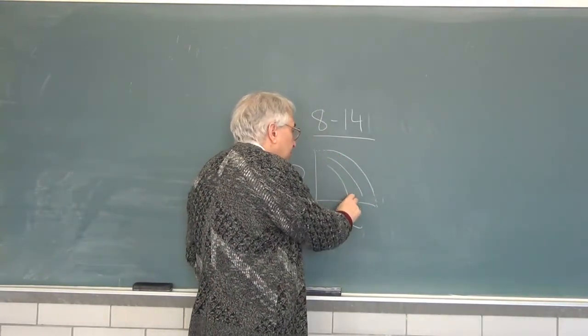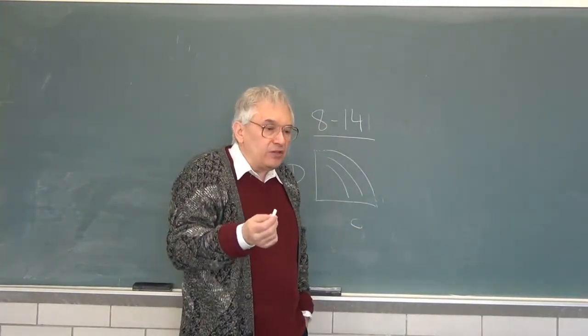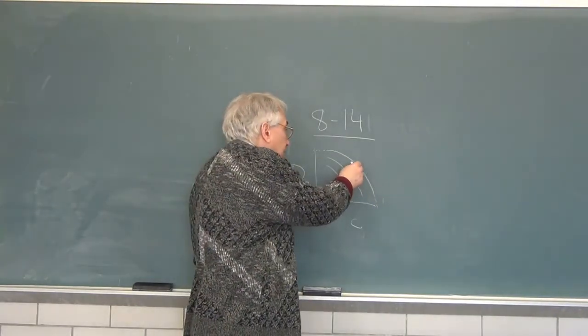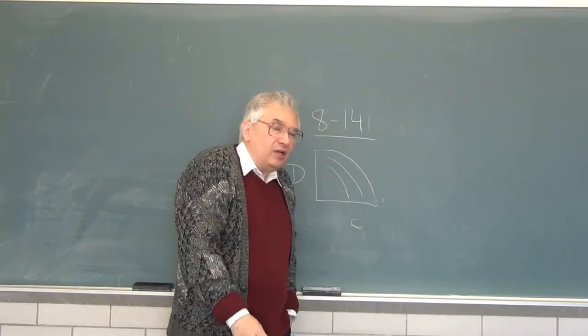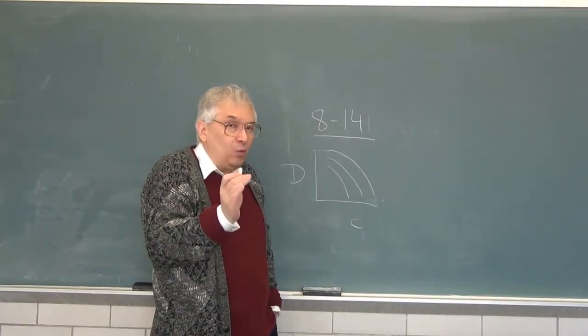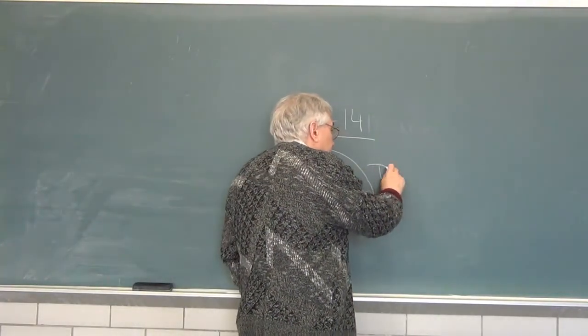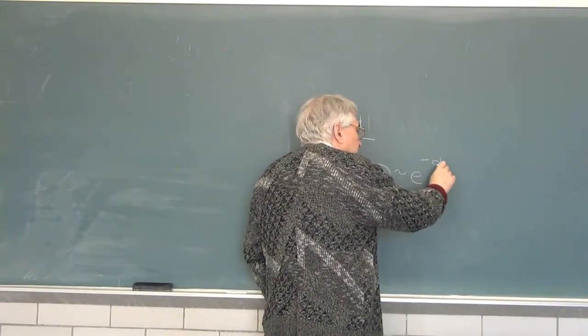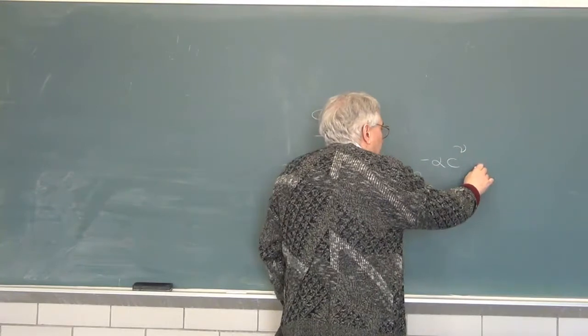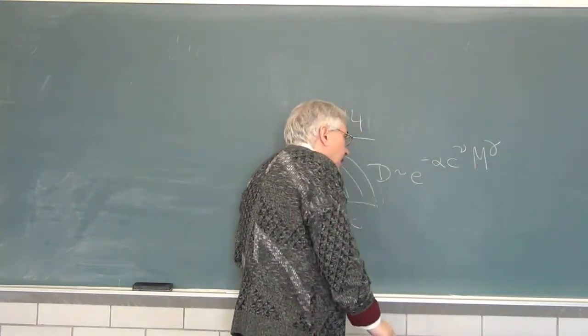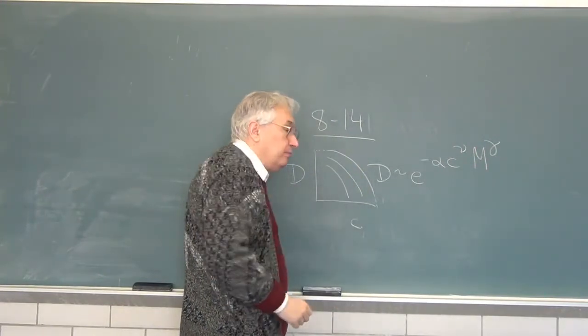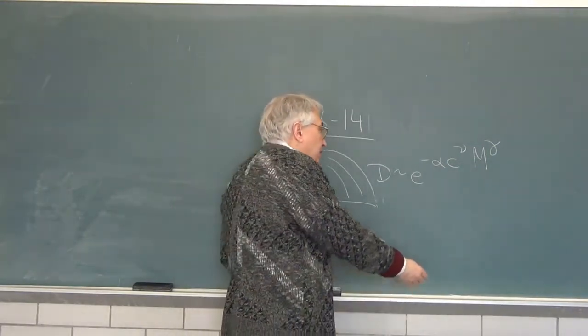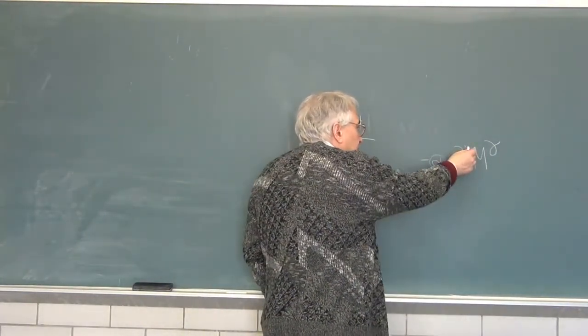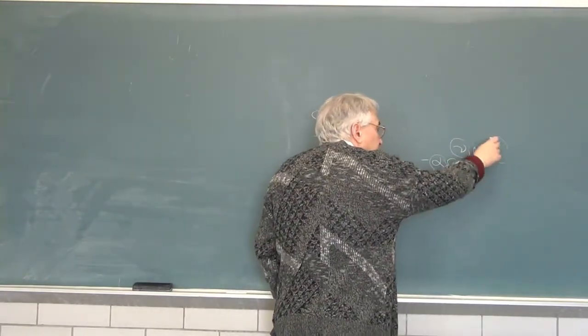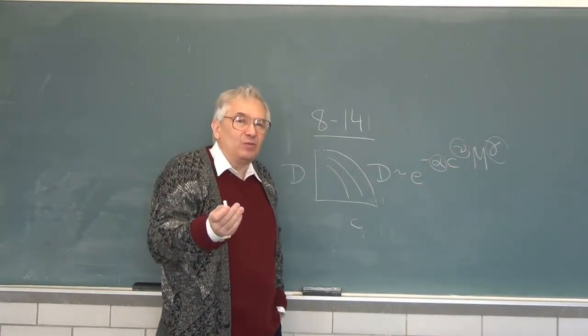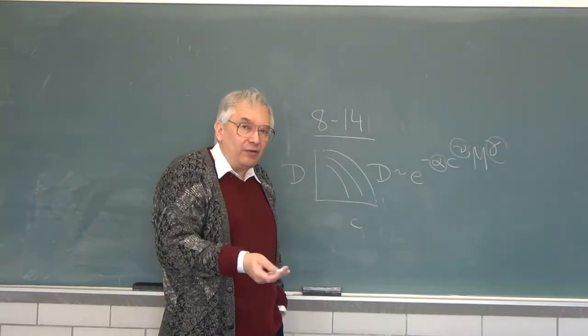For a series of these measurements, the work was done using polymers of several different molecular weights. And so for each polymer molecular weight, you see, oh, there's a stretched exponential. But in fact, for all of those different molecular weights, there is only one stretched exponential. The stretched exponential is D proportional to e to the minus alpha, some alpha, concentration to a power, polymer molecular weight to a power. And so, to describe the measurements at 3, 4, whatever molecular weights, you have a scaling prefactor, the concentration scaling exponent, the molecular weight scaling exponent. You have a very small number of parameters used to reduce a lot of different measurements.